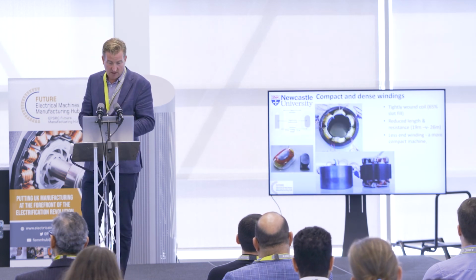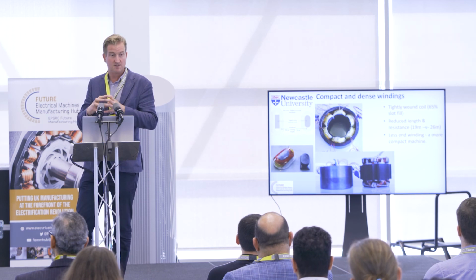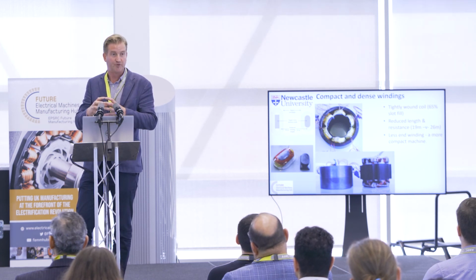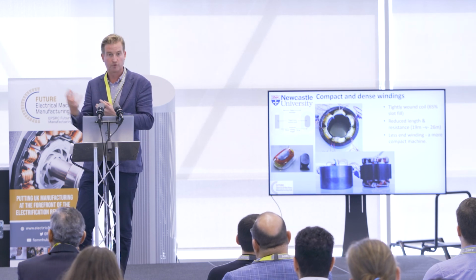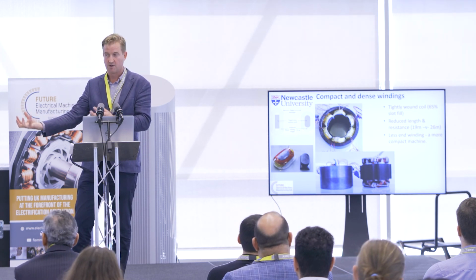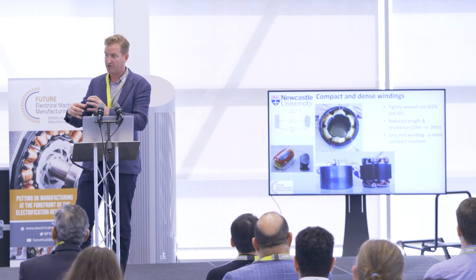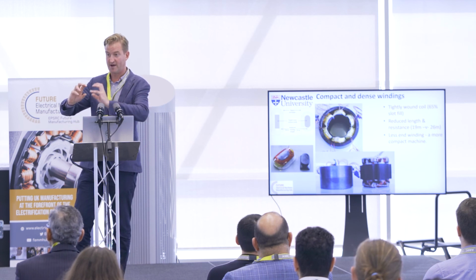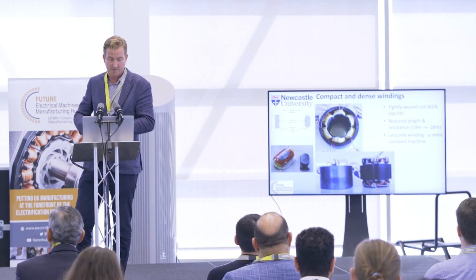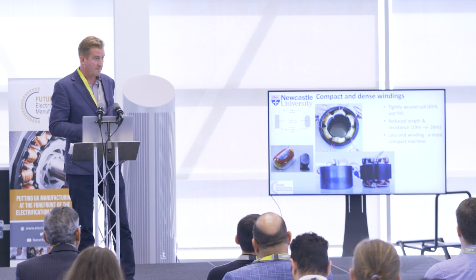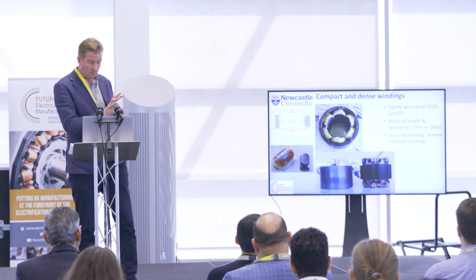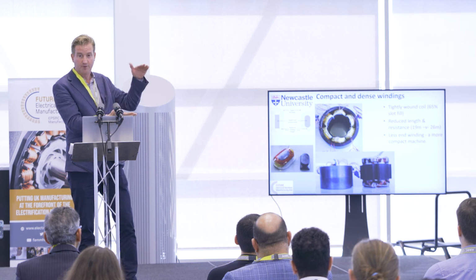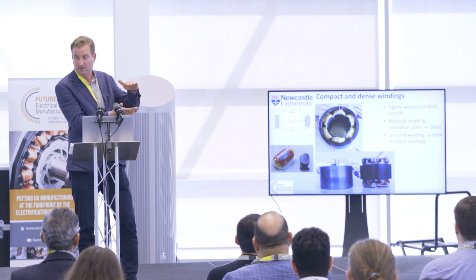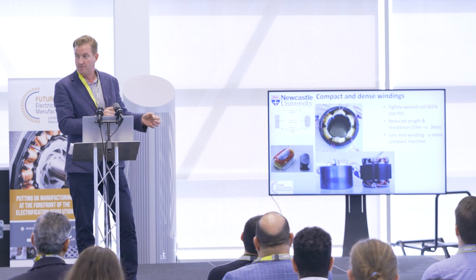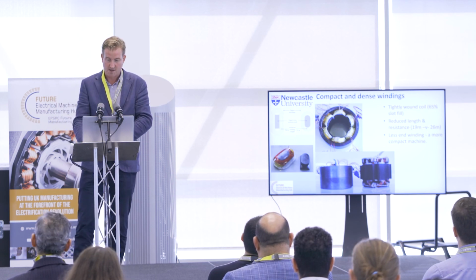We've looked at radial flux machines with rounded tooth tips. That enables us to have a nice tight coil. That coil could be produced elsewhere separately to the tooth and then placed over the tooth, or it would be possible to have a bobbin winding process where the coil is wound directly onto the tooth with suitable insulation in between. On the example here, this is a compressor motor. By having that shaped end winding, we were able to shrink the axial length of the machine, shrink the total length of the conductor, and thereby the resistance and the winding loss.